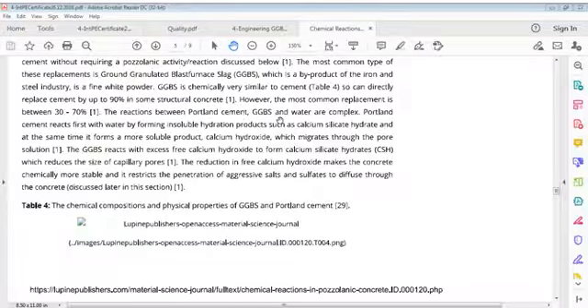Portland cement reacts first with water by forming insoluble hydration products such as calcium silicate hydrate, and at the same time it forms a more soluble product, calcium hydroxide, which migrates through the pore solution. GGBS reacts with excess free calcium hydroxide to form calcium silicate hydrates, CSH, which reduces the size of capillary pores.